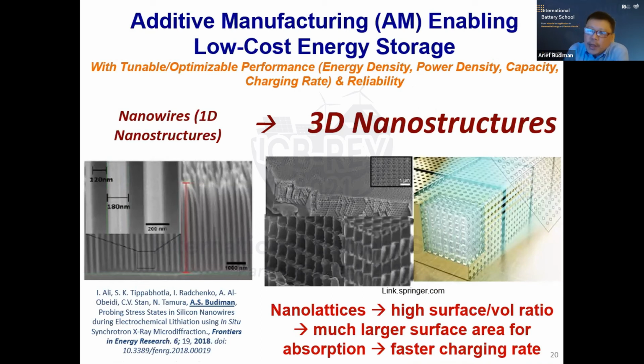So we see already the benefit of 1D nanostructures, which is nanowires, as we've seen. We have shown an anode made of pure 100% silicon nanowire. We are not trying to get maximum capacity in this case, because obviously the capacity is not going to be maximum. That's the reason why we want to go to 3D nanostructure. With 1D, the vertical space in between the wires is basically wasted space. This is space that we may use to hold ions, to hold charges, but we didn't. We didn't optimize it that way.